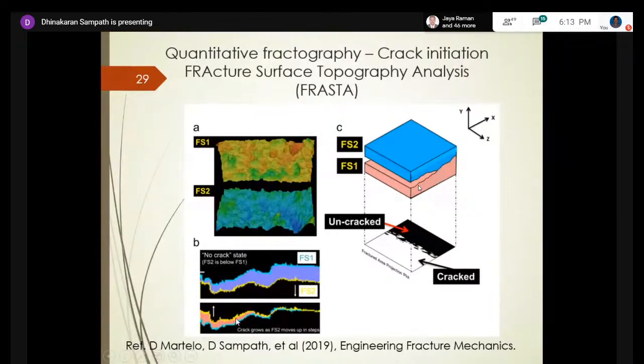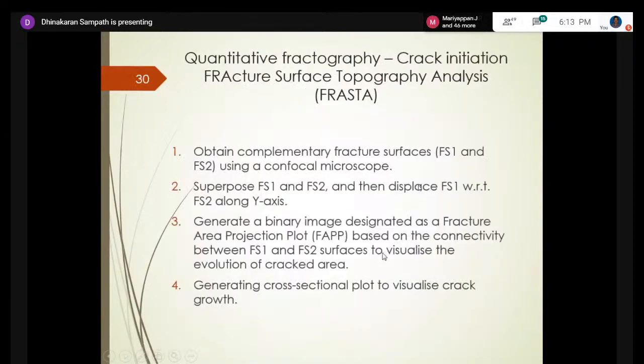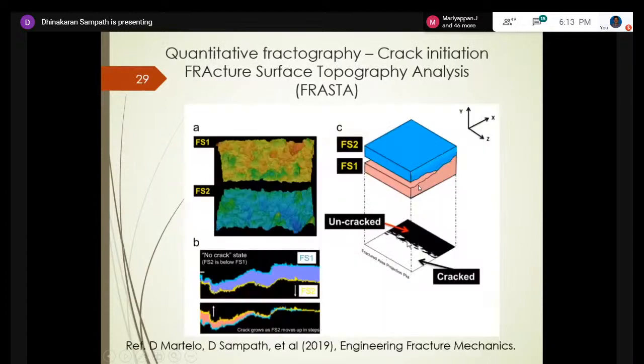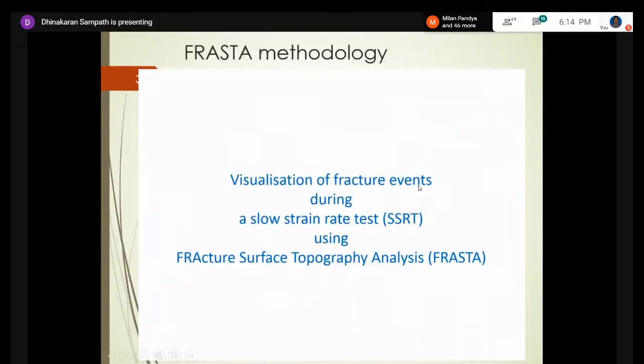And then lift the FS2 in this case, move it upward in steps, and then we see the connection between them. When the points on the surface are above the fixed one, they will be marked white, and those points that are below the fixed surface will be marked black. So we'll get a binary image, which is called a fractured area projection plot. This is the procedure explained here, and this is what we use to see how the crack evolution occurs from the topography.